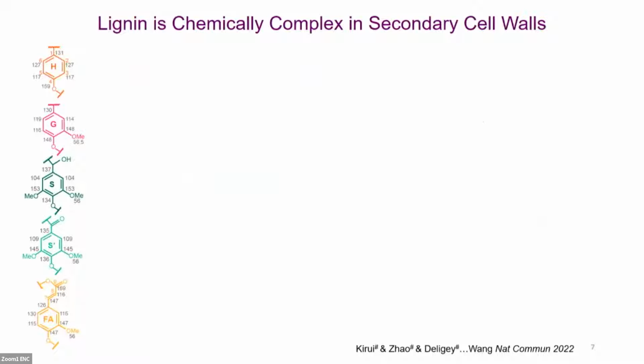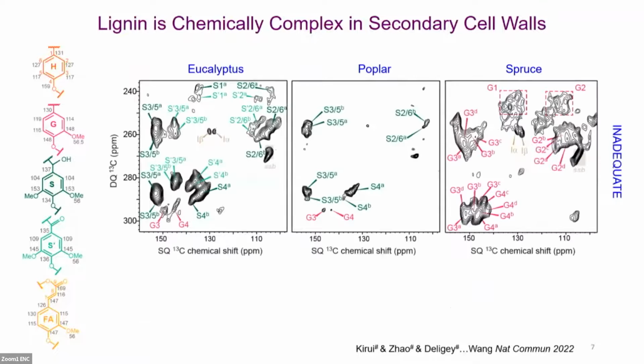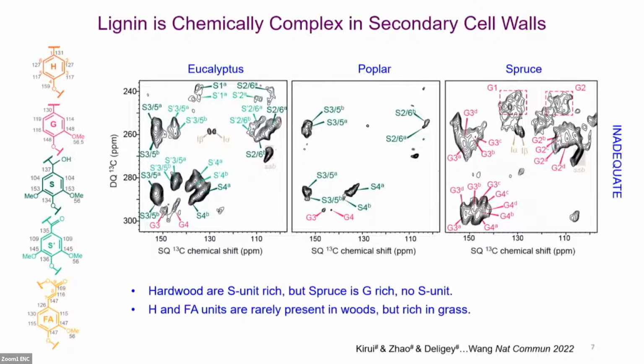Lignin is chemically complex. It is made up of aromatic rings connected by the lignin linkages. In our INADEQUATE spectra, we can clearly get the aromatic ring information, and we can see in the hardwoods, eucalyptus and poplar, the S unit is dominant, but the softwood only contains the G unit. When compared to our previous work, we know the H and FA units are rich in grass, but we cannot see them in our woody plants.